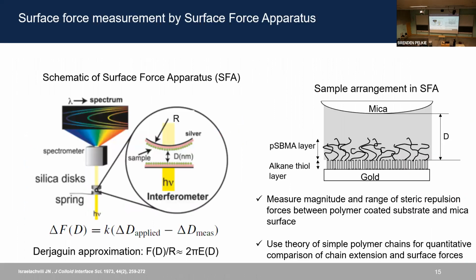And in order to do that, we used a surface force apparatus. So just briefly, how it works is that there is a white light that passes through two reflecting surfaces, and the reflecting surfaces are decorated with the molecules of our interest. So in our case, it was a gold-coated hemicylindrical silica surface on the one side, and we grafted different configurations of polysulfobetaine on gold. And on the other side, we have a back-silvered mica. And then after light interference happens, the light is passed through a spectrometer, which allows us to see the interference fringes, and we can measure the force from the deflection of the two interacting surfaces. And by applying the Derjaguin approximation, we can normalize the surface force in order to get the interaction energy.